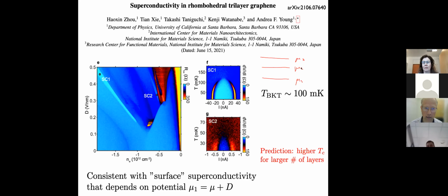And what they have done is that there's a D, which is the difference between these two potentials, and then there is this n, which is the overall charge density, which depends on the average potential. So my claim here is that if you can show that whatever you measure depends only on one of the chemical potentials, it's a slight indication of the fact that it's localized superconductivity. In this case, of course, it's not completely localized, but my point is that the delta would be somewhat larger on these surfaces than the center. Yeah, and that's what they have seen.